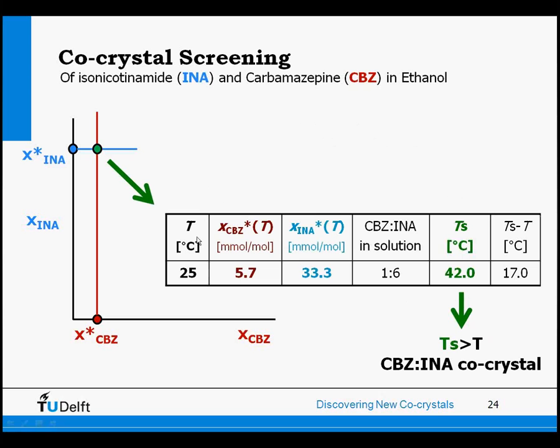So that's what we did. We took the solubilities of pure carbamazepine and pure isonicotinamide at 25 degrees, and that is 5.7 millimoles per mole for carbamazepine and 33.3 millimoles per mole for isonicotinamide. That is actually a ratio of 1 to 6 in the solution, so you need an excess of isonicotinamide. And then we measured the saturation temperature. And the saturation temperature of this composition is 42 degrees. So that is 17 degrees more than our reference temperature. So the saturation temperature is higher than our reference temperature, 25 degrees. So we have made a carbamazepine isonicotinamide co-crystal.